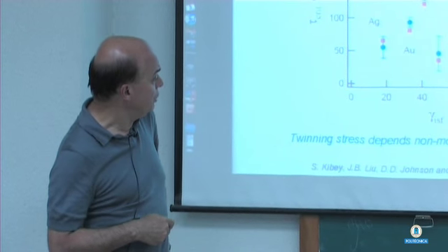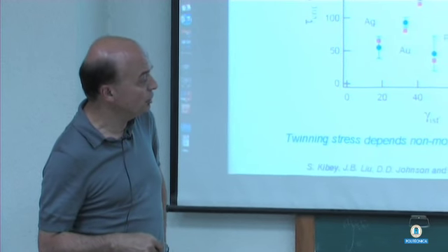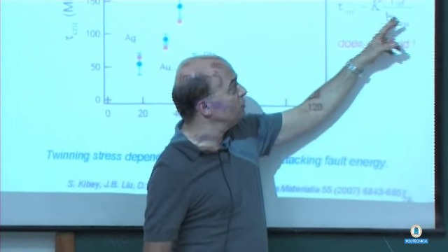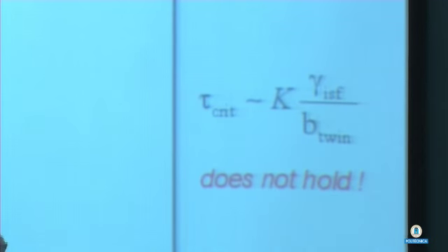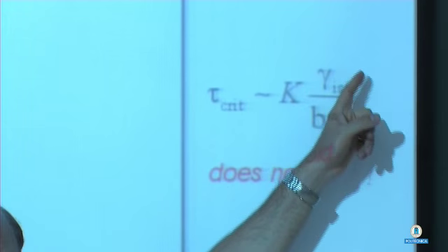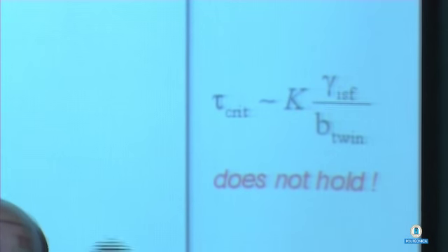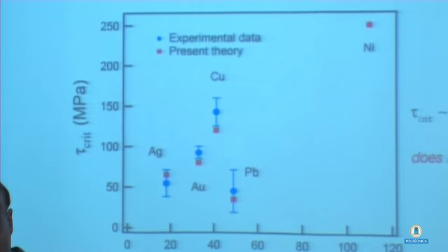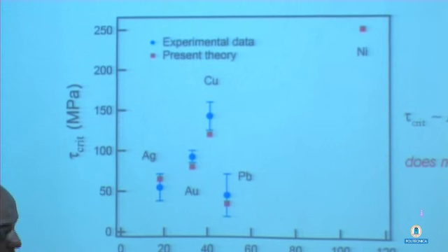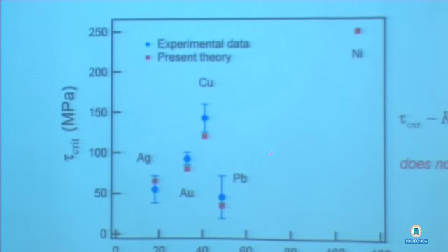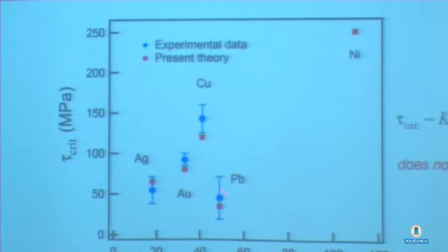Now, twinning stress depends non-monotonically on stacking fault energy. We taught our students that critical stress for twinning is proportional to gamma ISF, or some form of it. Maybe in that expression from Venables, there's an exponent here. But nevertheless, this is what's been taught in every textbook we have. But you could see that this correlation is not very good.